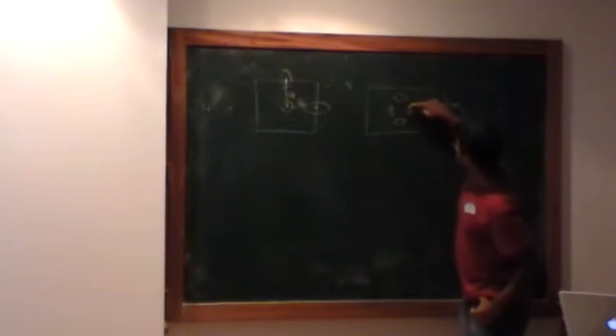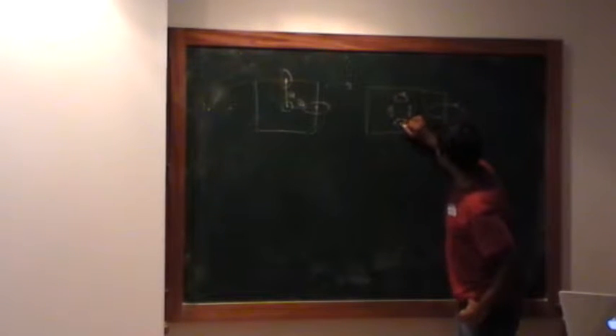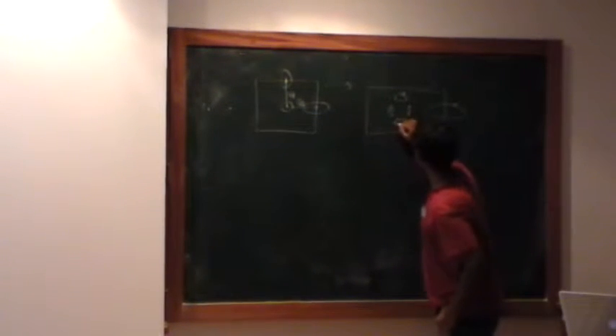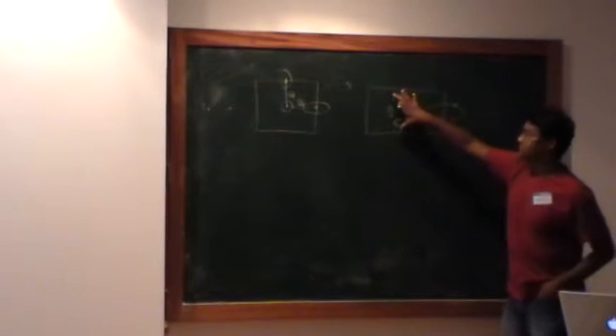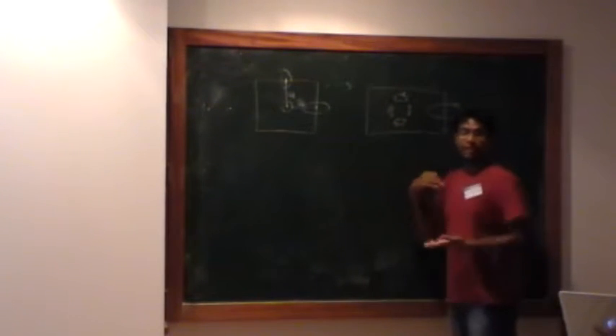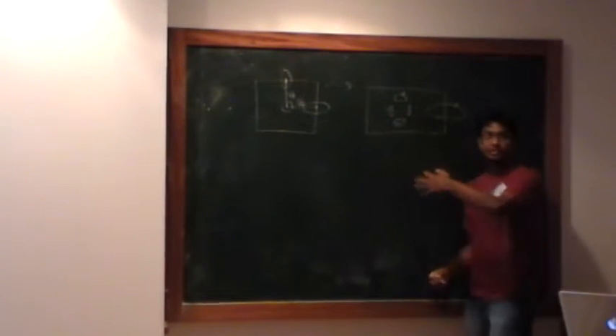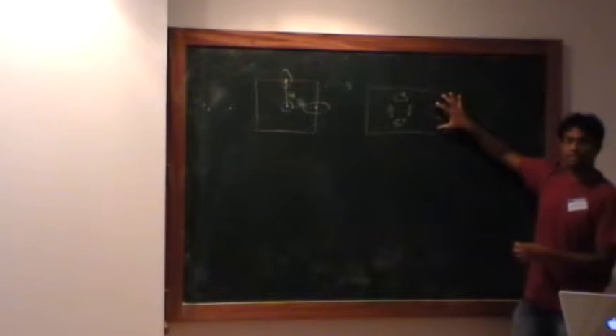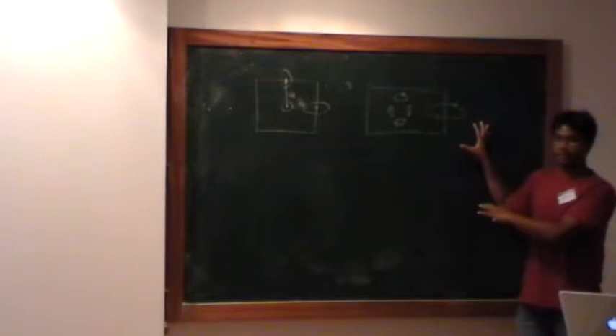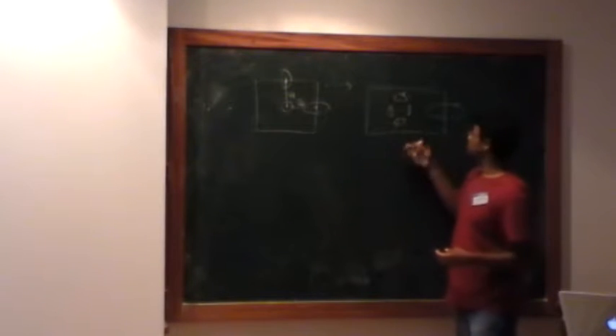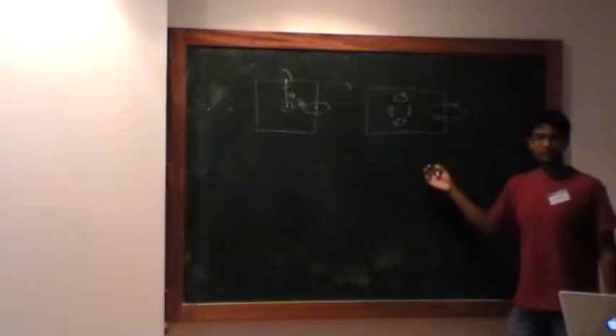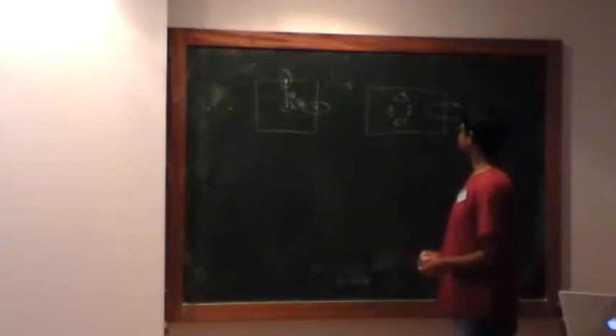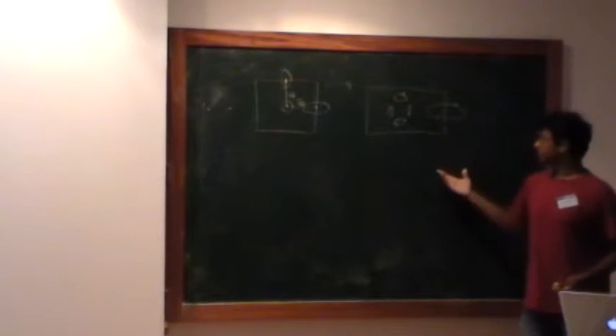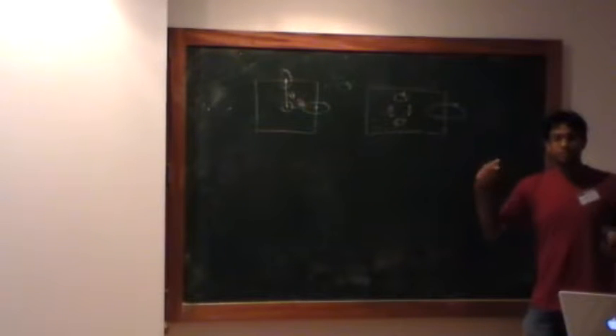From the residual pockets which are here, whatever interaction existed between these pockets, interaction still exists between these points which are K, minus K related. I'm sorry, it will be here. And superconductivity is possible even just within this. And this is, in my opinion, a slightly more interesting form of coexistence, so to speak, because it's the same electrons which form the magnetic order that are actually giving you superconductivity. It's just the residual fermions which are there. You don't even need the free band which is outside, which does not actually do anything to the magnetic order. This has been looked into before, and we are also looking into this to address the issue of loads, etc. After the summer school, something will be related to that. So that's essentially it. Yes, the answer is true, but then you have two different kinds of coexistence you can think of.